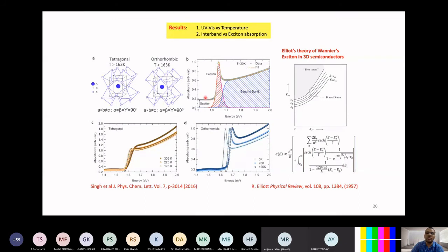So you can see that this is a typical example of the UV-Vis absorption spectra, and this data is at 30 Kelvin, and hence you see a very nice excitonic peak and a very steep absorption, and that can be fitted using this equation, Elliott's theory equation, which basically allows you to separate out the electronic band gap and excitonic contribution. In this excitonic contribution, there are lots of Rydberg levels, which are basically shown here, n equal to 1 to many, infinity. So these Rydberg levels can be seen if you do the experiment at even less than 1 Kelvin or something like that. So that is one observation.